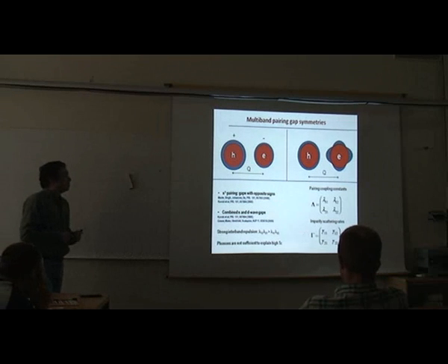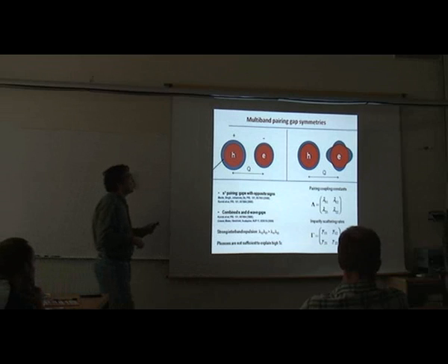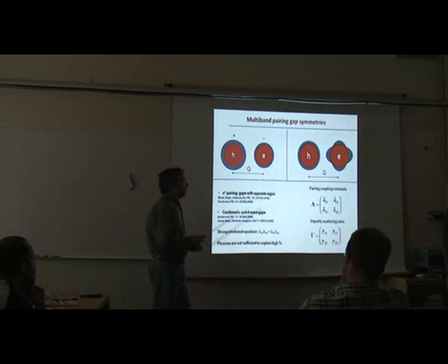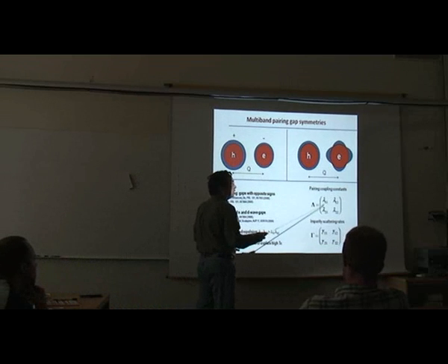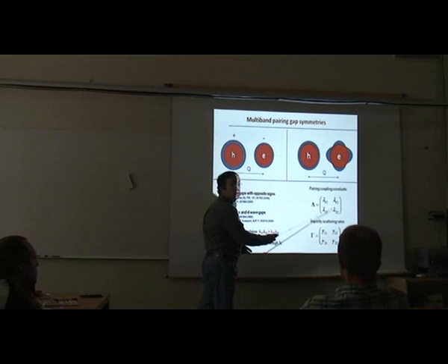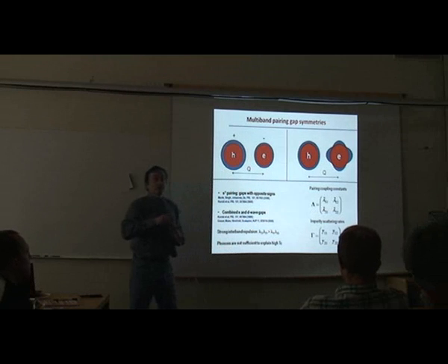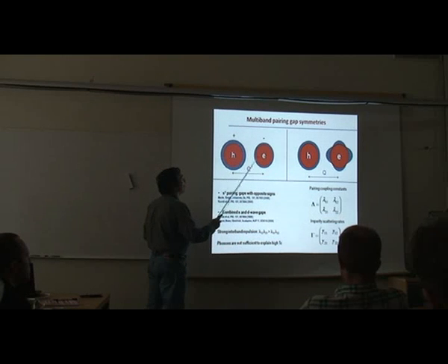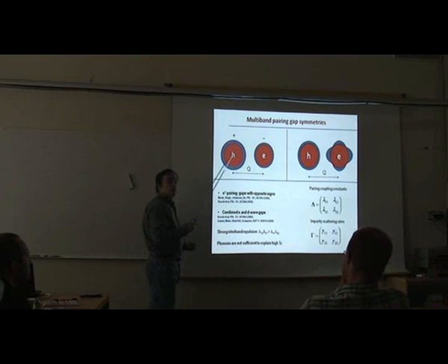And right away people suggested that actually pnictides are the materials in which the off-diagonal coupling is stronger than diagonal coupling. That means that superconductivity comes from the interaction between these two bands rather than the Cooper instability inside each of them.